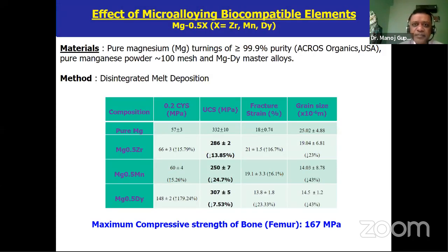So we tried elements like zirconium, manganese, and dysprosium. You can see that by adding these elements, the strength level may not be as good as magnesium, but it is always superior to that of the bone.